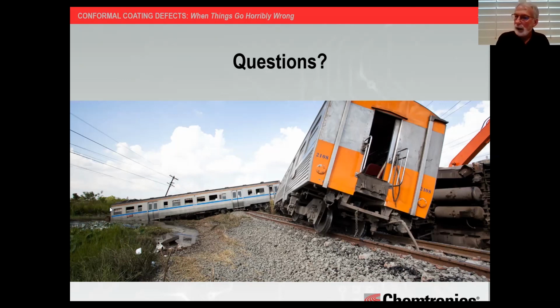But if you have ionic residue, as soon as that moisture vapor comes into that coating and it condenses, now you have a perfect setup for corrosion and dendritic growth. To address it and resolve it, the best way is just go back to that root and adequately clean that residual off, whatever it may be, whether it's from flux or some other type of residue, and completely clean that prior to your coating process.